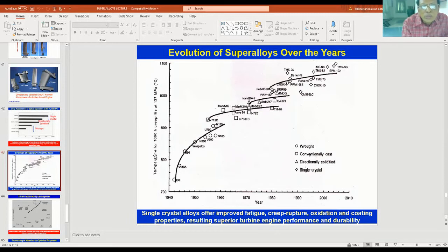Here, this is the temperature for 1000-hour creep life, plotted over the years. These are wrought alloys, and then we have conventionally cast alloys, and you have the directionally solidified superalloys, and now we have the single crystal alloys here. Over the years, the processing technology has changed, and it is a continuous process which is still continuing. Single crystals have to be produced on an industrial scale in order to put them in the engines and derive the benefit of using the engine at very high temperature.